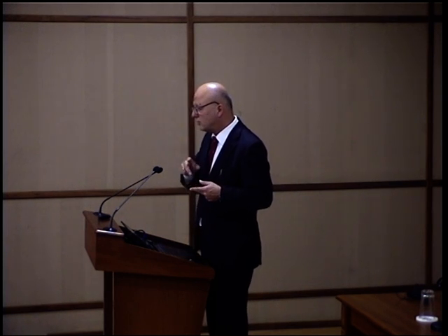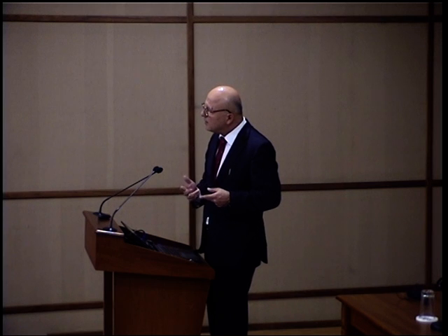You see here, we can steer the height or the length of these molecules by chemistry. And if we add some silane molecules, we make it longer or shorter. So in this way, we can steer the wavelength at which we have a cutoff, or where stray light begins. So here we are maybe almost no more in the range of Rayleigh scattering. Definitely we have no Mie stray light. This is the idea behind. So this is theory. Let us now come to reality.